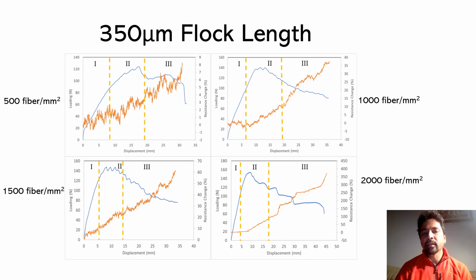And one additional thing we want to see here is for the 2000 fibers per millimeter square system, you see a corresponding increase in resistance for each drop in load value. That's a very unique thing you can observe in the 2000 fibers per millimeter square system compared to any other system.